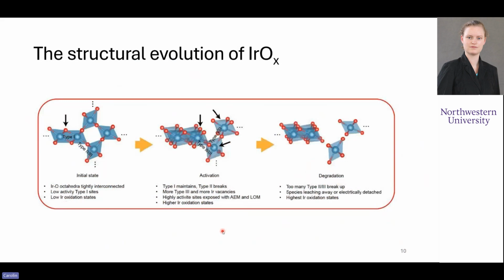this catalyst dies. And so this is highly significant, not just for the iridium oxides, because knowing what the structural motifs are that dictate the activity for water splitting means that we can use that to design the next generation of catalysts that will feature those specific design motifs. And that'll let us make much more active and much more stable catalysts for water oxidation without needing this really high iridium loading. And hopefully that'll let us make a dent in the challenges that prevent PEM water electrolysis from being commercially viable at a large scale at the moment.